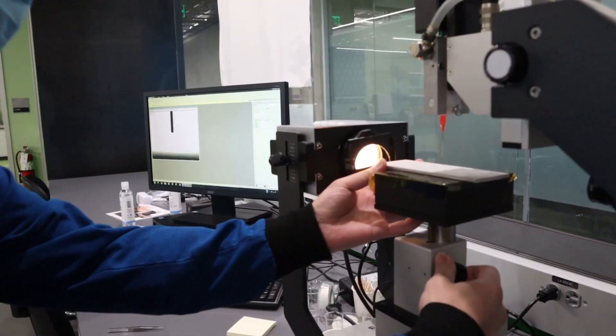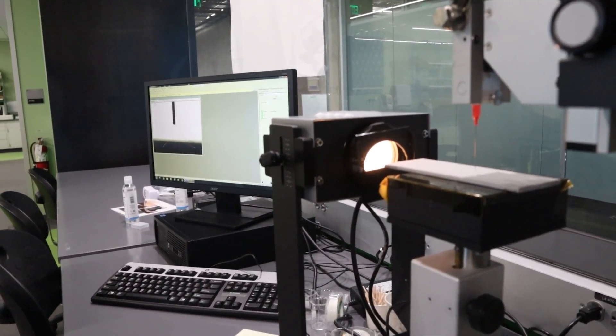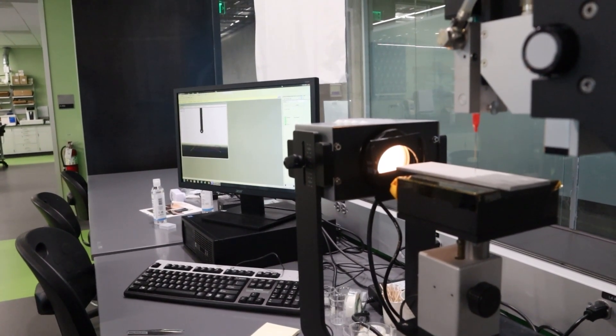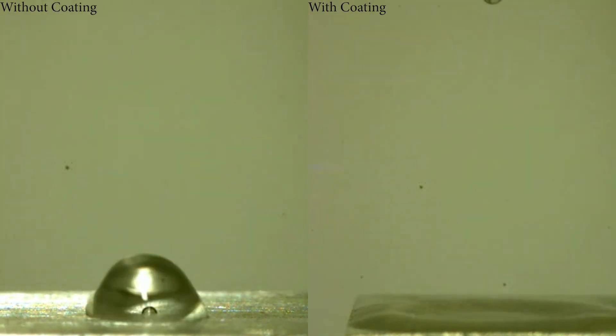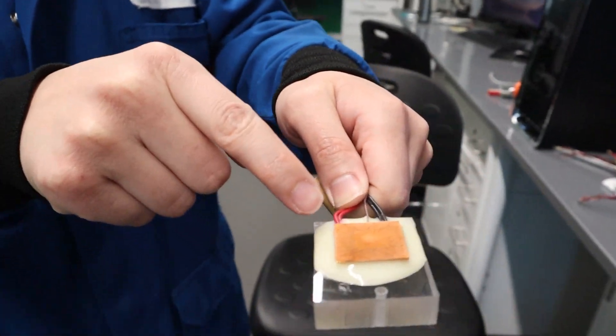The other coating is called nanoscale surface coating, which can provide a broad range of wettability — extremely wetting versus extremely non-wetting. When you have an extremely wetting condition, it spreads the liquid into a wider area such that evaporative heat transfer is enhanced. When it's non-wetting, we can effectively collect condensation drops.